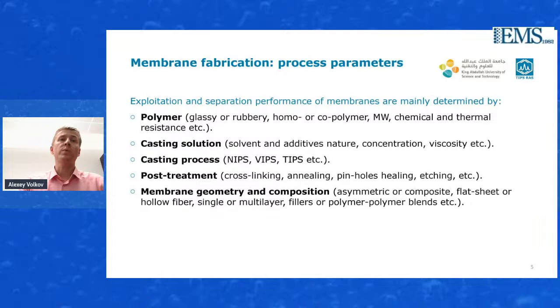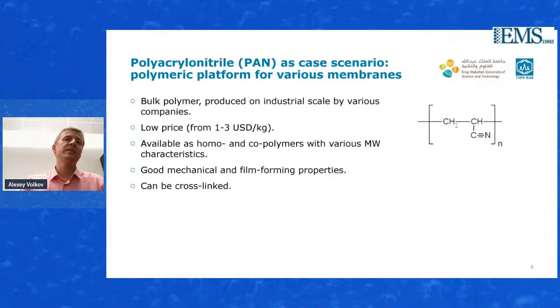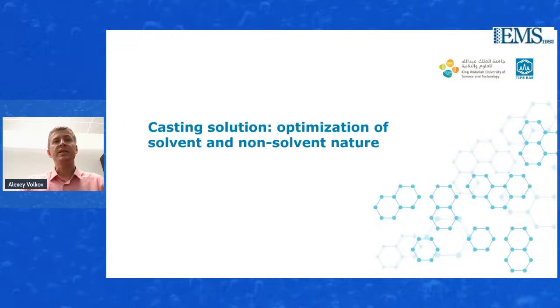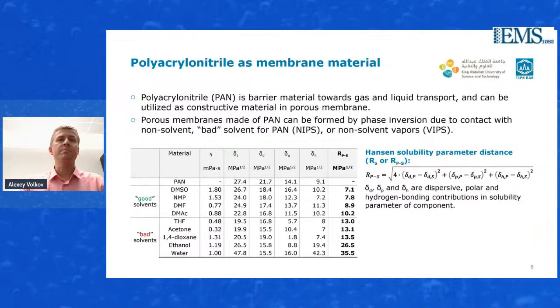And when we'd like to make a membrane, we need to focus on different aspects, such as the polymer, what kind of polymer we'd like to use, what the casting solutions are, and whether or not we need a post-treatment. And from that point of view, I think it's quite interesting to still consider polyacrylonitrile as a good platform to fabricate various types of membranes. First, I start with how the casting solution, how the solvent and non-solvent nature might impact the preparation of the membrane. As we know, PAN is not a selective material, so we cannot make a selective layer made of PAN, but PAN can be used as a constructive material to form porous membranes.